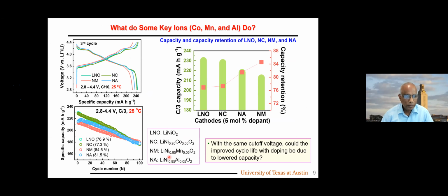One thing to remember is as we go from LiNiO2 to doped material, there is a decrease in the capacity if we limit the cutoff voltage to a certain voltage, for example, here 4.4. So we have to keep that in mind. With that cutoff voltage, if you look at the cyclability, obviously the aluminum and manganese doped material cycle better than the undoped LNO or NC.